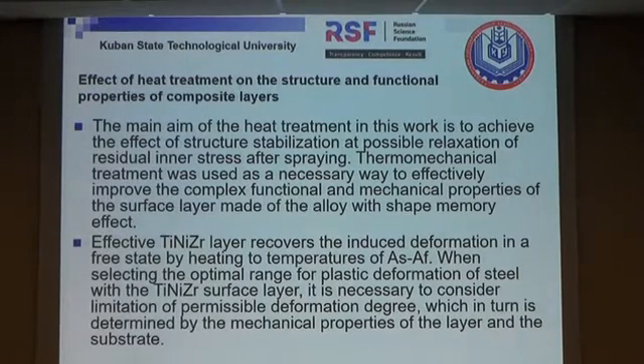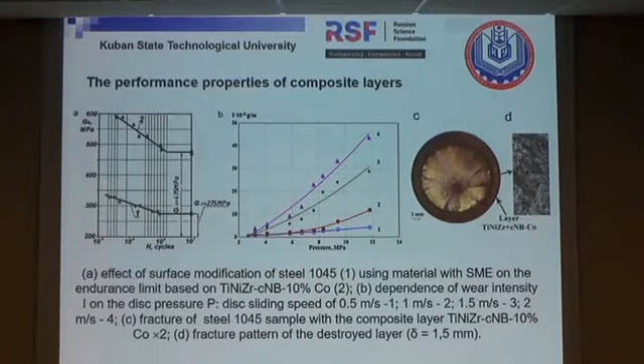In titanium nickel zirconium, the shape recovery of the induced deformation in the martensite state occurs on heating to temperatures As/Af. When selecting the optimal range for plastic deformation of steel with a titanium nickel zirconium surface layer, it is necessary to consider the limitation of permissible deformation degree, which in turn is determined by the mechanical properties of the layer and the substrate. The performance properties of the composite layer are represented here.